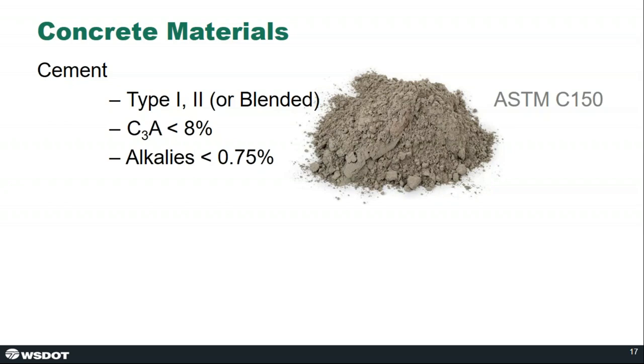For cement, we're using type 1, type 2 cements, sometimes blended cements, just general use cements. We don't allow type 3 or higher early strength cements. That's oftentimes a challenge for delivering to distant job sites, but it also creates a risk of thermal strains and thermal cracking due to a higher heat of hydration and potentially a higher rate of heating and cooling.